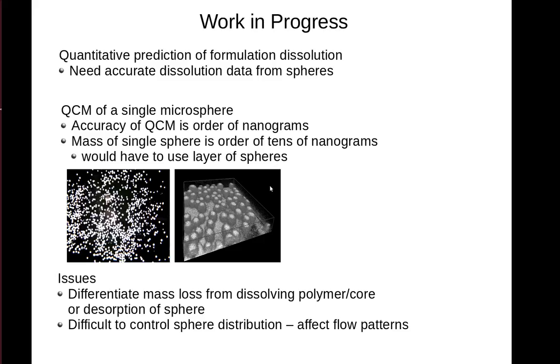The work in progress is we would like to see if we can quantify the information that we're gathering from the QCM, OCT, and the ATR measurements. To do that, we will need accurate dissolution data from the spheres. One method is to put a sphere on top of the Quartz Microbalance and measure a single sphere dissolution. Unfortunately, the mass of a single sphere is on the order of tens of nanograms, and the resolution of the QCM is on the order of nanograms, and therefore we really don't have the resolution for a single sphere.